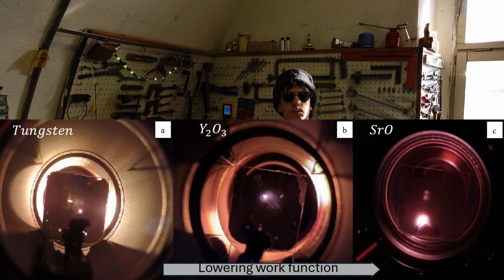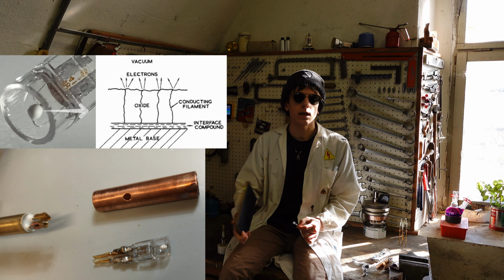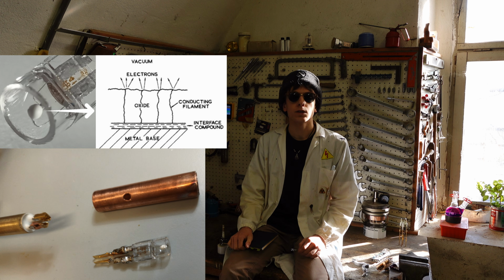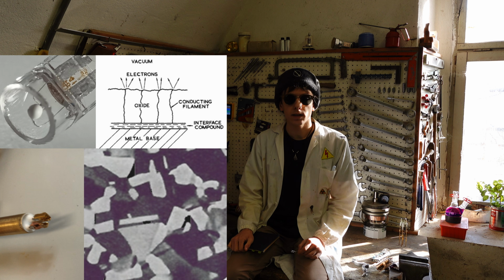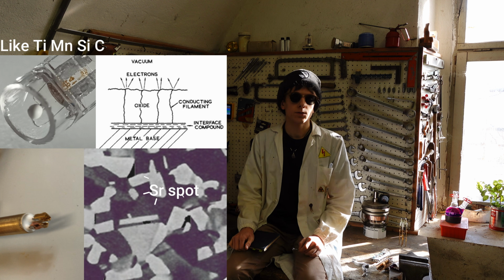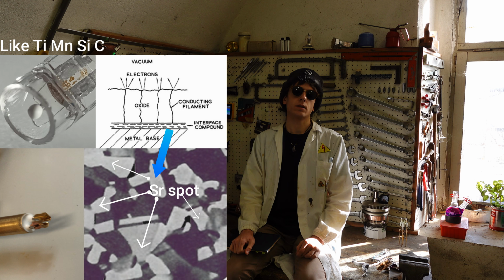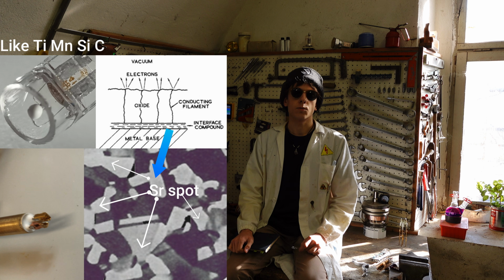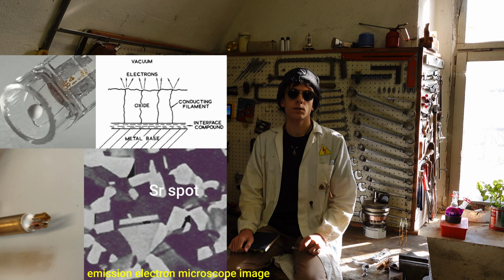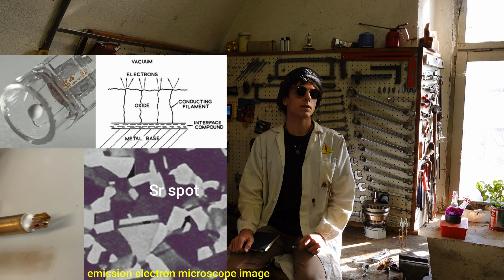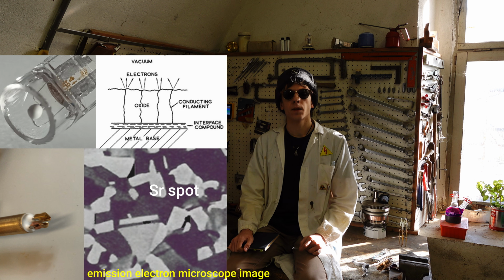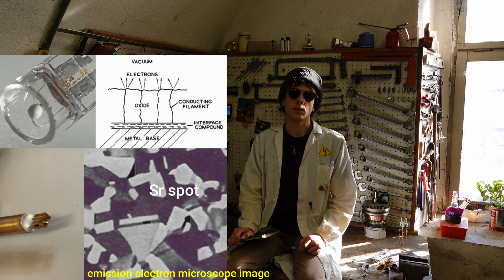A very important aspect to make this type of oxide-coated cathode work, that we don't have time to discuss now, is activation, which takes a dull and useless metal oxide into a wonderful emitter of electrons. During this process, part of the oxide is converted into the corresponding metal at the boundary of the filament due to the scavenger species present. This metal is a lower work function emitter like strontium, and being at a high temperature it emits electrons by thermionic process, way more than tungsten does.